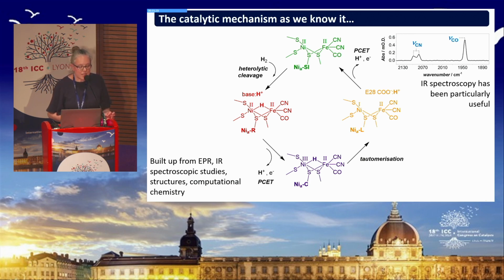The remaining steps in the catalytic cycle involve a series of proton-coupled electron transfers where in this first step here, the proton that was released from hydrogen cleavage moves out through a series of amino acids or ordered water molecules in the protein and leaves the active site region, and an electron is also transferred out through the chain of iron-sulfur clusters, leaving the nickel oxidized up to nickel-3.